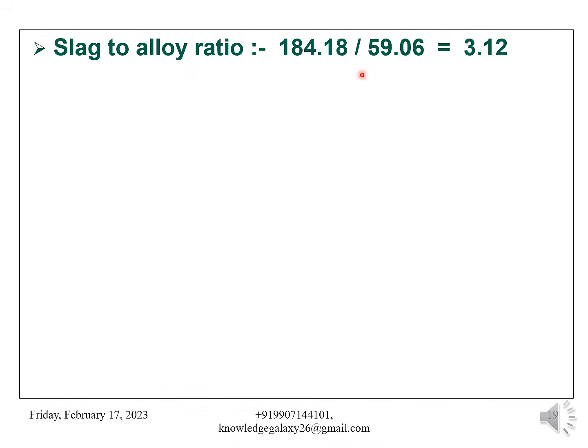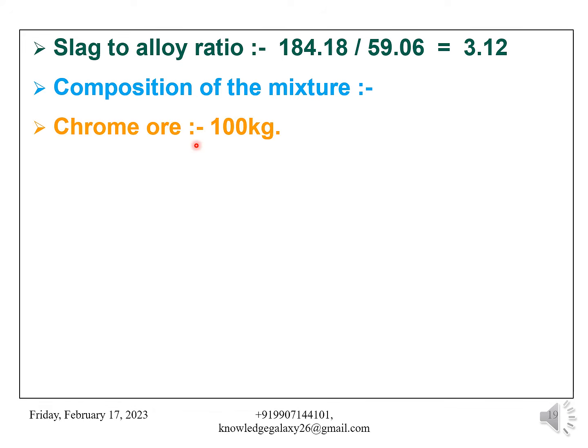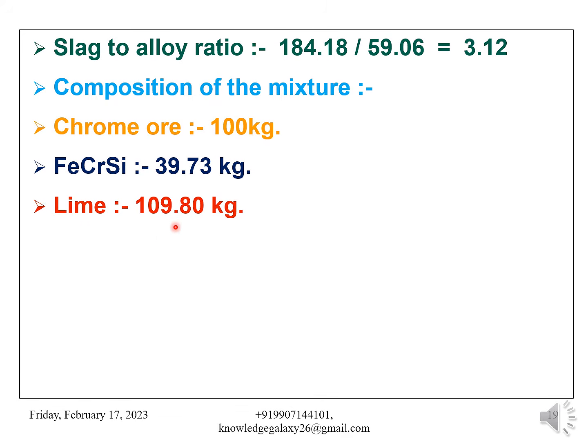Slag to alloy ratio is calculated as 184.18 divided by 59.06, which is equal to 3.12. Now the composition of the mixture is summarized as chrome ore 100 kg, ferrochrome silicon 39.73 kg, lime 109.80 kg.